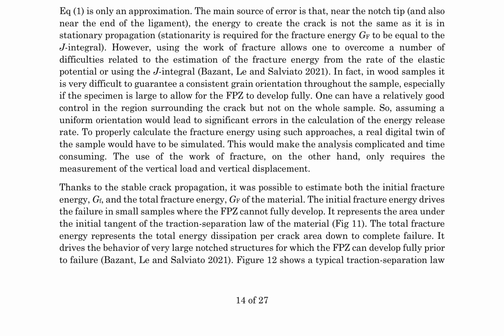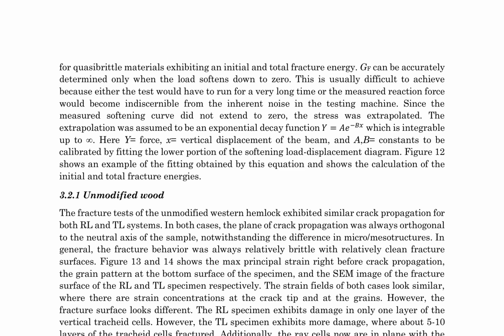The total fracture energy is emphasized as the driving force behind the behavior of very large notched structures, where the FPZ can develop fully prior to failure. Fracture tests were conducted on unmodified Western hemlock wood samples in both radial-longitudinal (RL) and tangential-longitudinal (TL) systems to investigate crack propagation and fracture behavior. The results show that crack propagation occurs orthogonally to the neutral axis of the samples, regardless of differences in mesostructures. The fracture behavior is characterized as relatively brittle, with clean fracture surfaces observed.